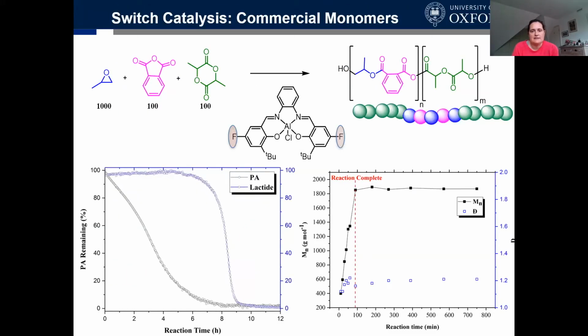And we began by studying these insertions just from mixtures, and we exposed it, in this case, to an aluminium catalyst. And when we look at the consumption, we can see that the first thing that happens is the anhydride is consumed, and then after about 8 hours, the lactide begins to be consumed.